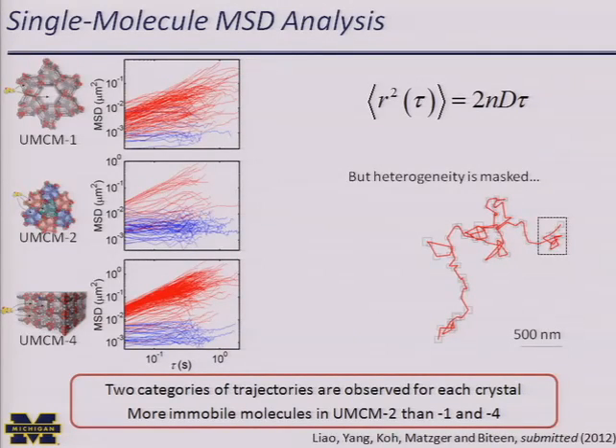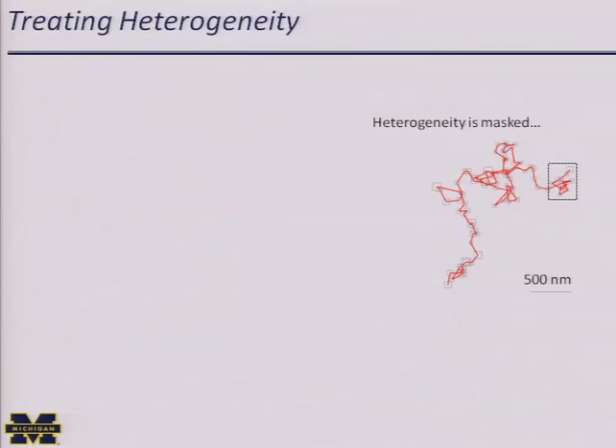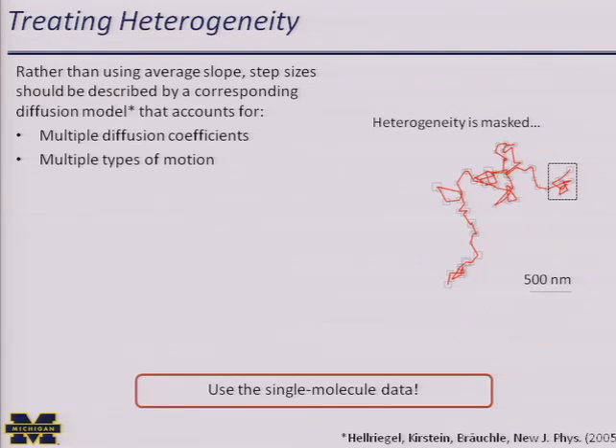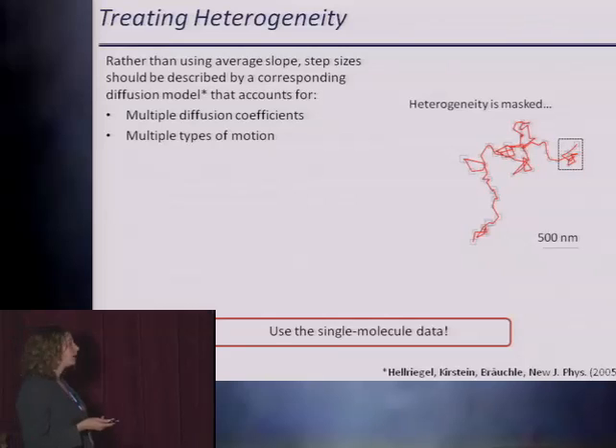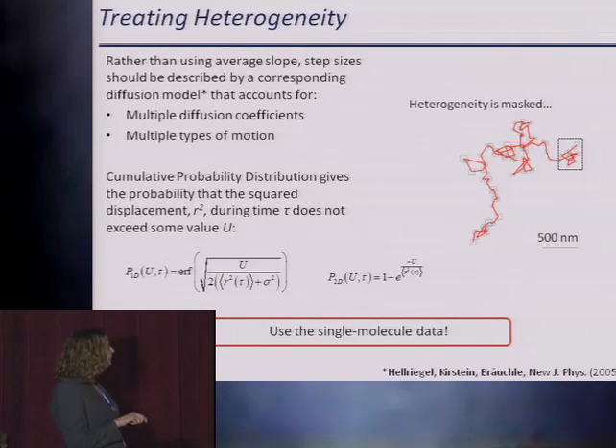And heterogeneity, again, is masked because each of these, as powerful as it is that each one is one molecule, if we look at a track like this, there's a lot of free motion, but then there's some confined motion that I've highlighted with that black square. So to treat the heterogeneity, we want to use a diffusion model that accounts for multiple diffusion coefficients and multiple types of motions, actually using the single molecule data. And so we want to use the cumulative probability distribution, or the probability that the squared displacement does not exceed some given value in some time period, to really look at what's going on.